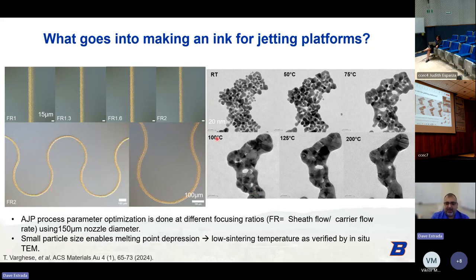We've since improved on our process and gotten better control of the kinetics to control the particle size. And so if we can reduce the particle size to sub 10 nanometers or around 10 nanometers, even if we have just a few of those in the distribution, we can induce a melting point depression in the gold. So gold typically melts at about a little over 1,000 degrees Celsius, but in this reduced nanoparticle size form, we can see through in situ TEM analysis that we are starting to get good sintering at as low as 50 to 75 degrees Celsius, where the particles are starting to coalesce.